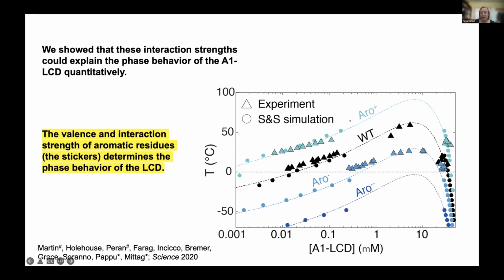So if we go to this Aro plus variant, which has a larger number of aromatic residues than the wild type here, then we need a lower protein concentration to first hit this coexistence line, to first get phase separation, than for the wild type, then the Aro minus variant. And it also explained why we never saw phase separation for the Aro minus minus, which was missing two thirds of the aromatic residues, because its critical point is actually below freezing.